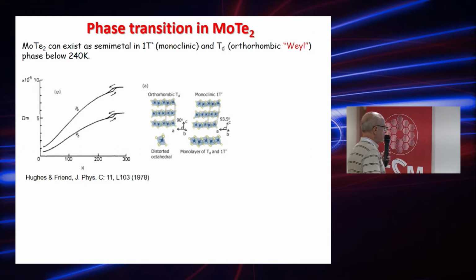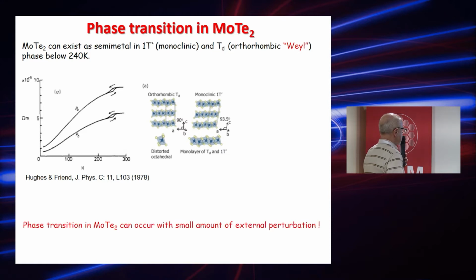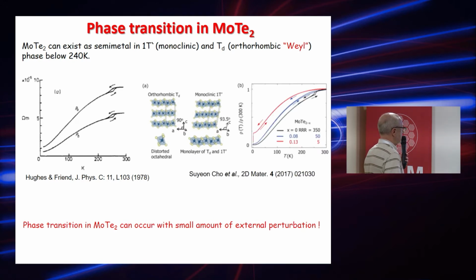What is interesting about these two materials is that, for example, molybdenum ditelluride can exist as a semi-metal in a monoclinic form and an orthorhombic form. This transition occurs at 240 K and produces some hysteretic behavior in resistivity, so this is a first order phase transition. This transition is very sensitive to small amounts of external perturbation. For example, if we have non-stoichiometric material, with a deficit of, for example, tellurium, this phase transition disappears.